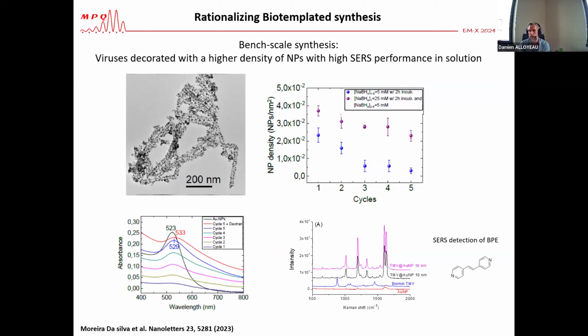We need to bring concrete information to colloidal chemists to convince them that in situ information can change the way they are fabricating materials. And those nanomaterials, you see that from the optical point of view, they have this absorption that is now very wide, and you have absorption in the infrared region, and those hybrid nanosystems are also very efficient for SERS detection in solutions. So that's ongoing work.